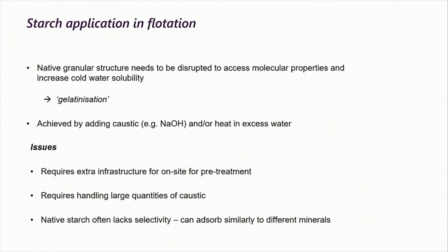If you're going to use starch in flotation, you have to overcome its granular structure, and that's what we call gelatinization. It's usually achieved by mixing the granules in an aqueous environment with caustic usually, or with heat. But if you're going to do this on site, there are a couple of issues. You're going to have to have infrastructure like preconditioning tanks for the pre-treatment. You're going to have to handle the caustic, and that can be in some environmentally sensitive areas. And in general, native starch as it stands doesn't have the best selectivity. So that's one of the things that we were trying to develop and advance in my work.